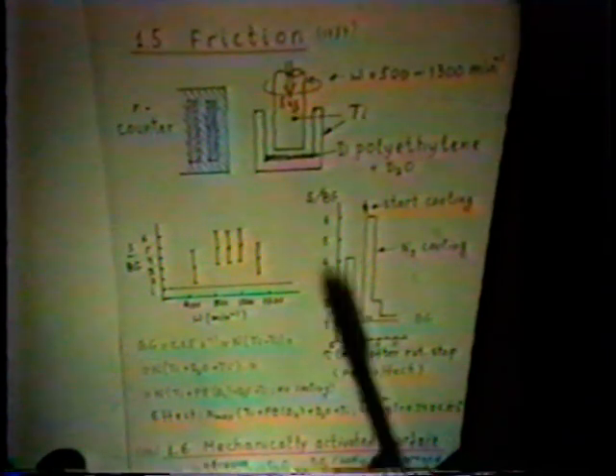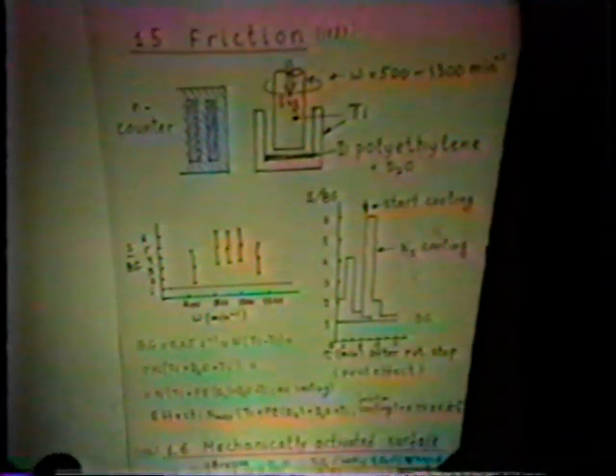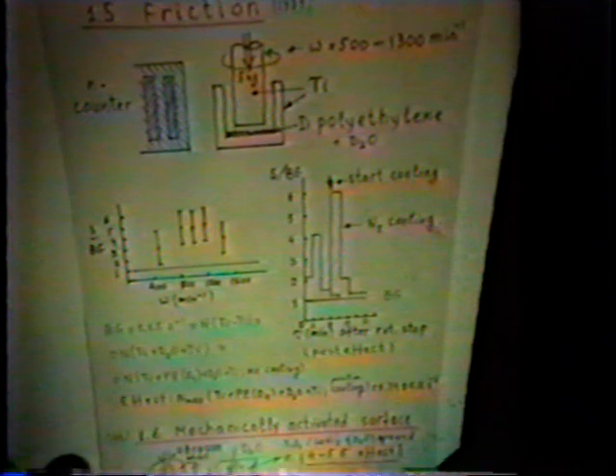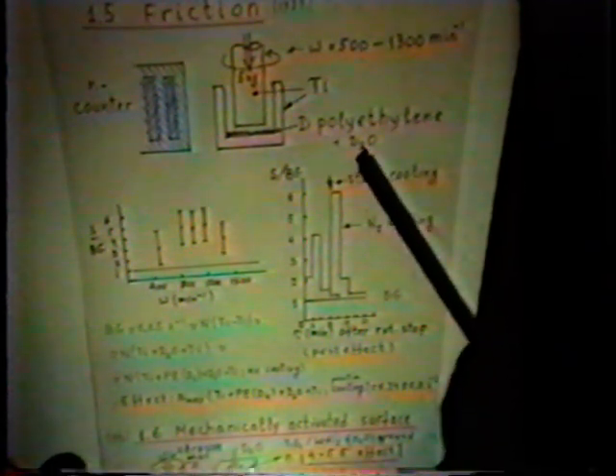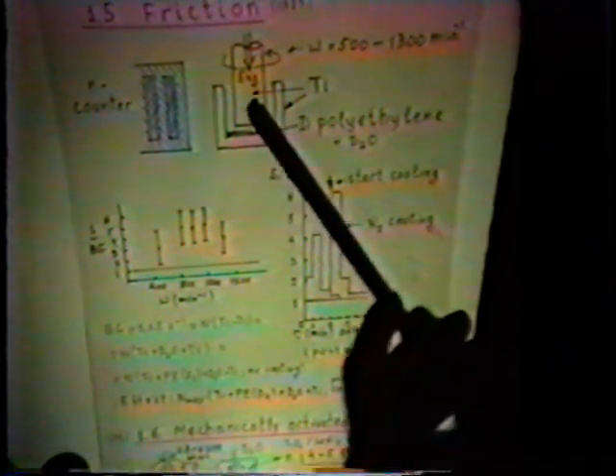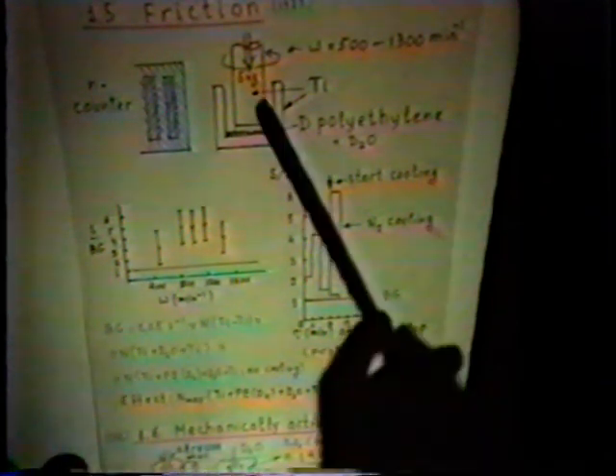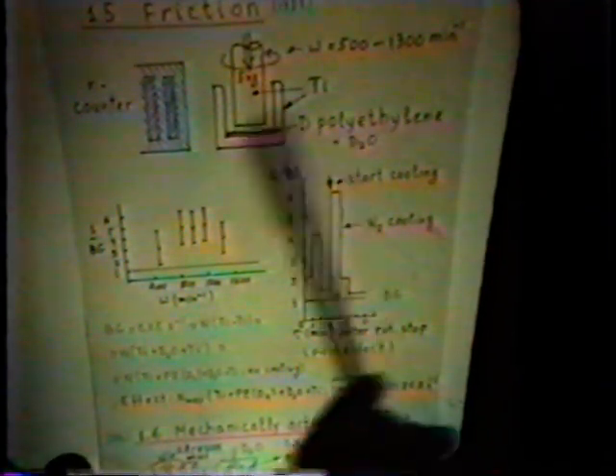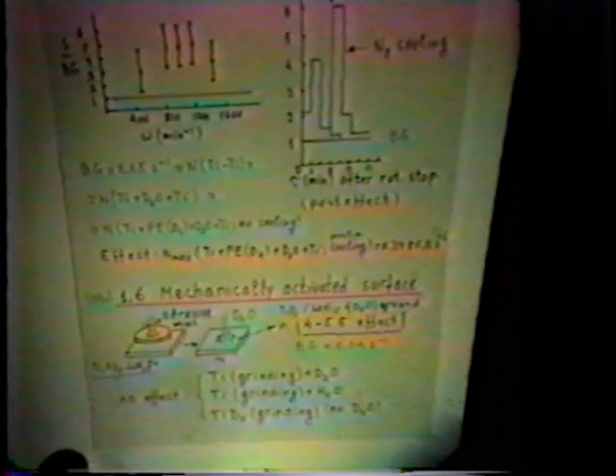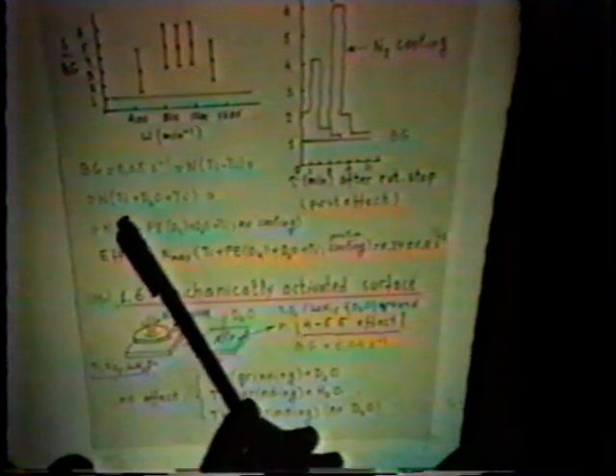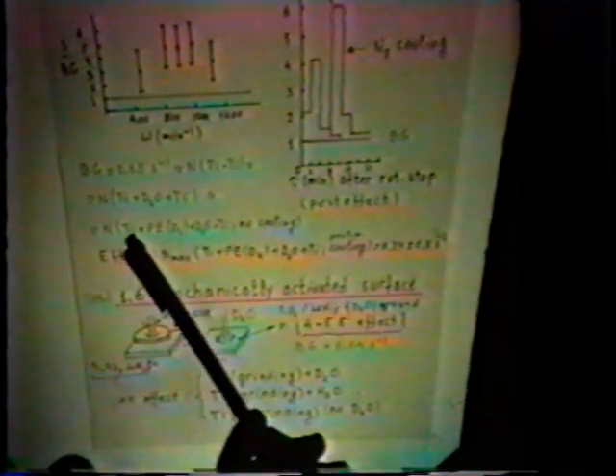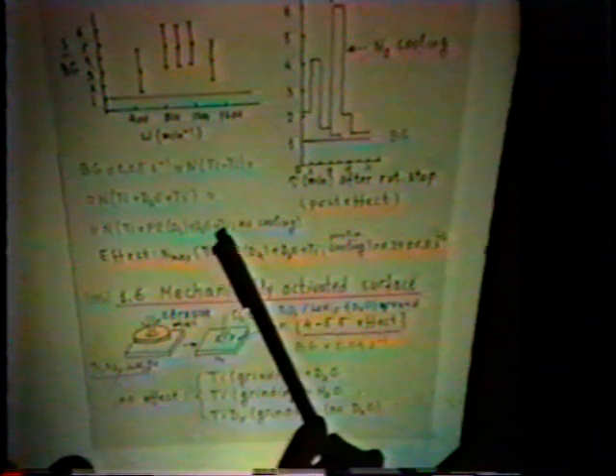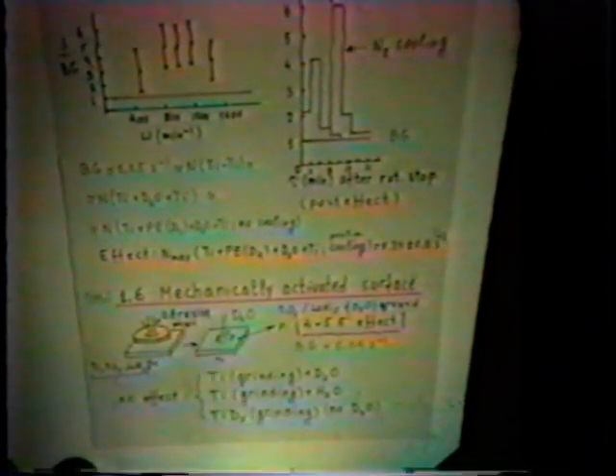The next experiment was neutron measurements in the course of friction. In this case, deuterated polyethylene and heavy water were placed inside of 2 titanium surfaces, and the upper one was pressed and rotated, and they measured neutrons. First of all, they observed that for the following combinations, titanium, heavy water, titanium, polyethylene, heavy water, titanium, the signal was practically at the background level.